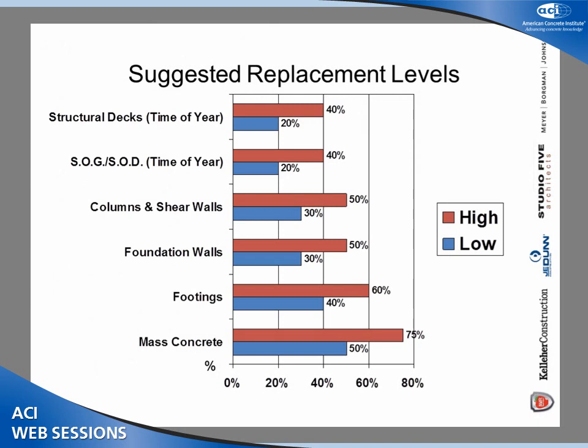The higher values are, I'd say, the blends or the replacement values that I use, with the possible exception of January and February in this neck of the woods. So for structural decks, we're up to 40%. We try to get that, and we did use that on the rec center. Slab on grade, slab on metal deck, the same. We kept them up at 40% all the while.